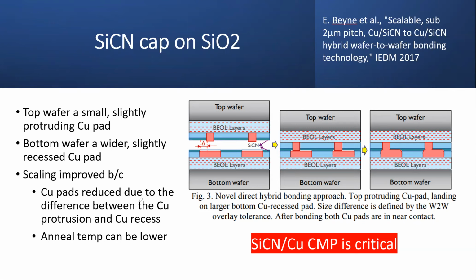And then I could reduce the height of the copper pad, and that could help me scale it. And I also proved that the anneal temperature can be lower. So this is what they propose. It's kind of a pretty good idea. They published it in 2017. I don't know which one adopted it, but it's a pretty good, novel idea. But they mention themselves that the silicon carbon nitride and copper CMP is critical. Forming something like this is not an easy thing, because SiCN is deposited on top of the SiO2, and then you have to polish in a way that some recess and some stick out in a well-controlled manner. Wow, that's not an easy job. But that's the idea.